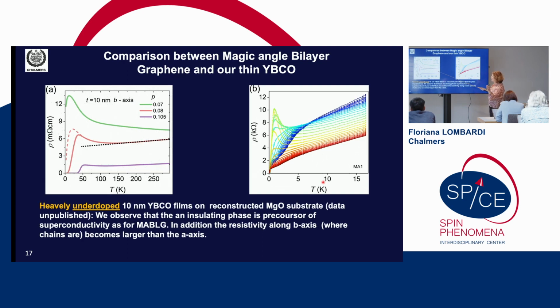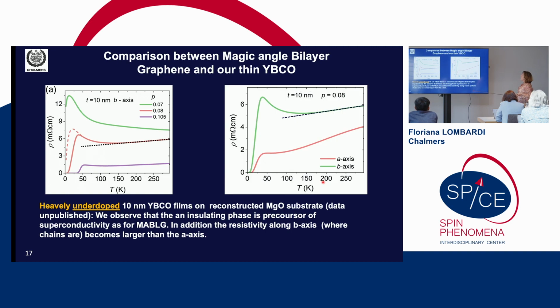When you go to very low doping, because what I showed you before was at 1/8 doping, so intermediate. But if you go towards the Mott insulator, what we get is a similar R versus T to what has been obtained in magic angle graphene. So you have a linear-in-T resistivity and insulating behavior before superconductivity sets in. And even more interesting, at this low doping, the resistivity along the B-axis becomes much higher than the resistivity along the A-axis.